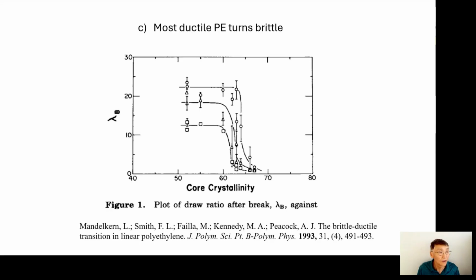your polyethylene, when it's crystallized enough, it's brittle now, right? That's Mandelkern's work. Why? If you give enough time, which is the bad thing, so you want fast crystallization. If it's slow crystallization, the chains have time to attach onto the crystalline phase. In doing so, they completely rearrange the network. The network does not have enough of this uncrossability anymore, because the crystalline phase cannot tolerate it, right? So fast crystallization is the magic. Polyethylene works, even polypropylene works, because they crystallize sufficiently fast so that the network is preserved.